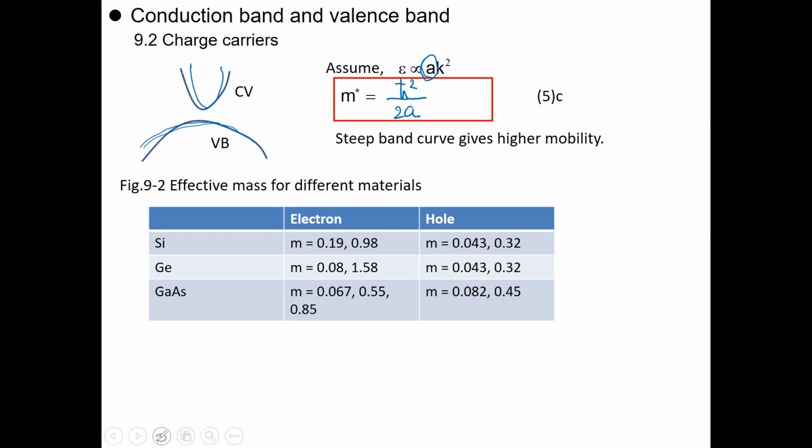The other important point is that the band structure is more complicated. Depending on the state or position the electron is in, the effective mass varies. Depending on which valley the electrons are staying in, the mass itself is different.